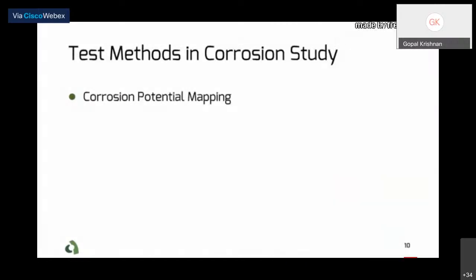The first concept is the half-cell potential. In this method, surface potential measurement is used to predict the probability of corrosion. While the test provides useful information about the chance of corrosion for the area under investigation, the results can easily become misleading if the potential effect of influencing parameters are not appropriately taken into account. Another limitation of the test is that it does not provide any information about the kinetics of corrosion reactions.